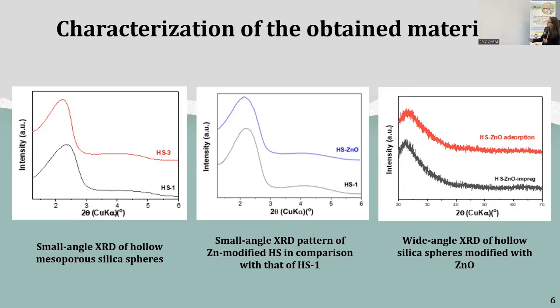The small angle XRD pattern of zinc modified hollow silica in comparison with that of pristine silica also shows an ordered pore mesostructure. And the wide angle XRD pattern of hollow silica modified with zinc oxide suggests that zinc oxide nanoparticles are amorphous or very small.